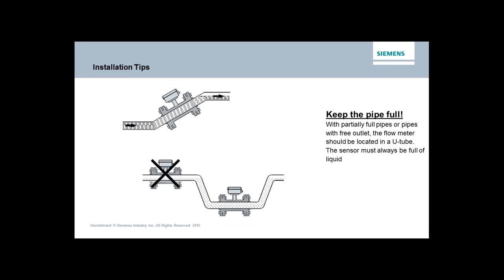Now, if your pipe is full, 10 feet per second may equal 50 gallons per minute. If your pipe is just above the midpoint and covering the electrodes, but above that there's no liquid, it's still going to say 10 feet per second, but that 10 feet per second may only be 27 gallons per minute instead of 50. So it's important that the pipe be full. The ideal way to mount a mag meter is vertical with the flow going up. That way, as long as it's flowing, the pipe is going to be full.